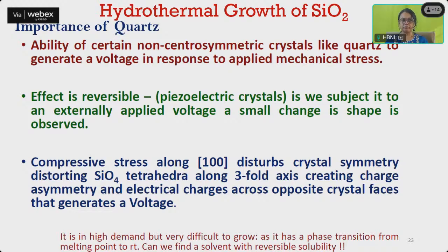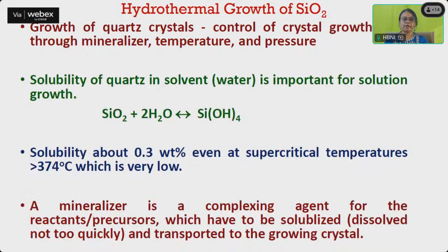It has very high demand but is very difficult to grow, as it has a phase transformation from the melting point to room temperature. So we have to find a solvent. How is the quartz crystal grown? It is dissolved in water using a mineralizer. The solubility of quartz in water is important for solution growth. But this solubility is around 0.3 weight%, even at a supercritical temperature like 374 degrees, which is very low. It is very difficult. You have to take the water to 374 degrees centigrade, and even then its solubility is very low.